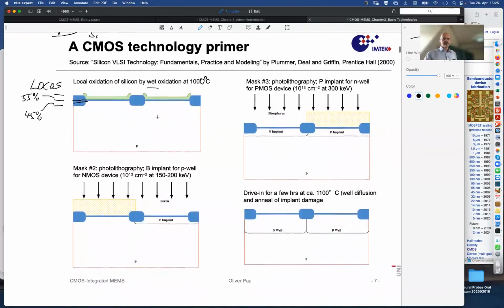Yeah? Okay. So now that we have the field defined, we know where transistors can be elaborated, namely in these two regions. And so one is going to be the NMOS and one is going to be the PMOS transistor. So what is happening next is that one of those areas is protected against ion implantation by a photoresist. And that photoresist now lets you do some ion implantation. So basically a directed injection of dopants, boron in this case, which are able to reach the silicon even through this little thin oxide that still remains. This pad oxide is still there.